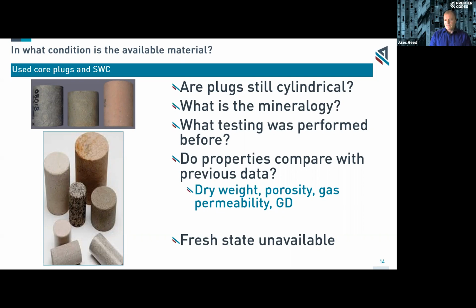But of course, with these routine core plugs, the one measurement that you are always unable to make is fresh state analysis. Because fresh state can only ever be fresh once, and that's when we first obtain the sample from a core, take a plug from that core, and begin to use it directly after the coring process.